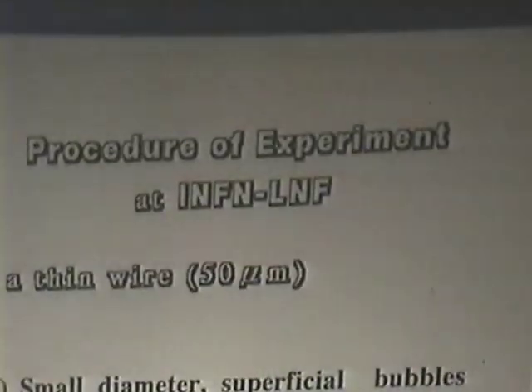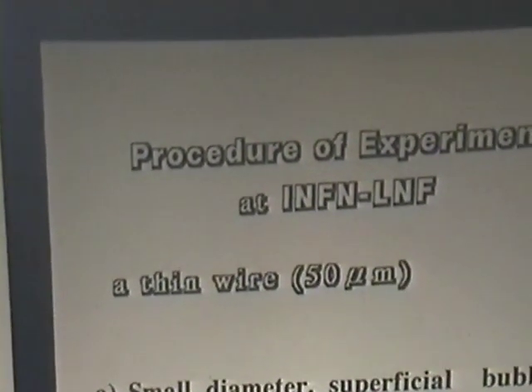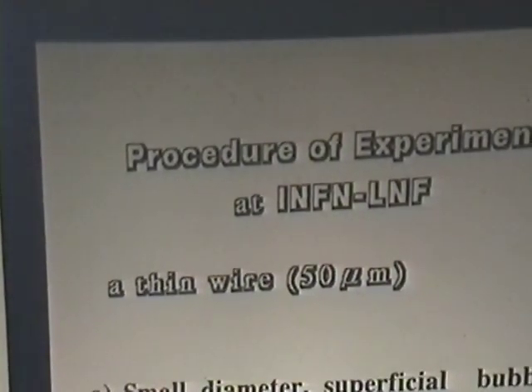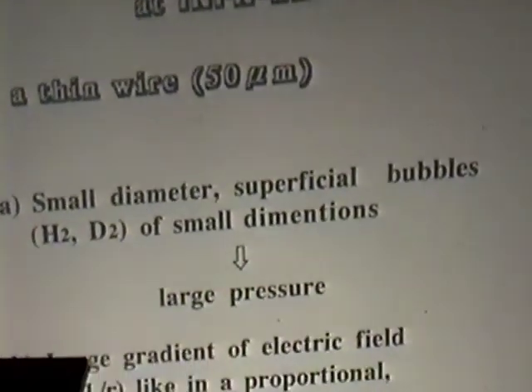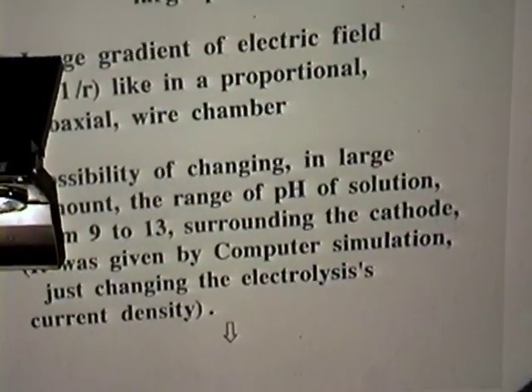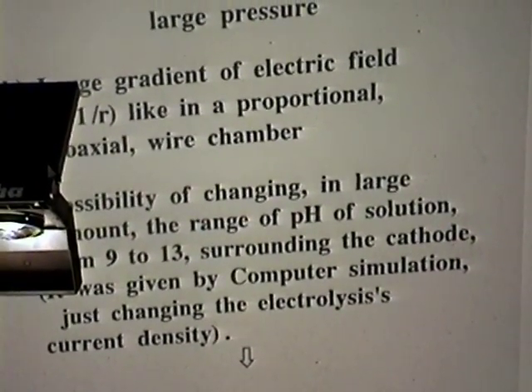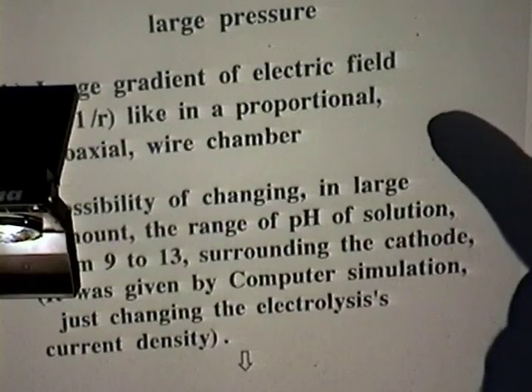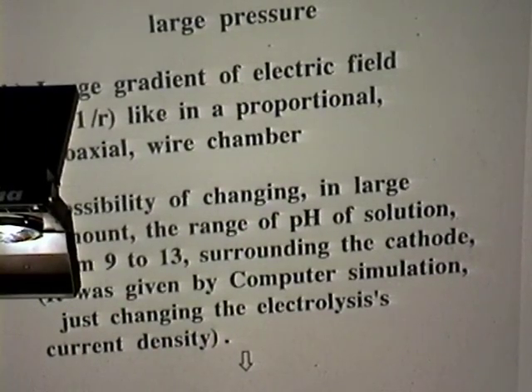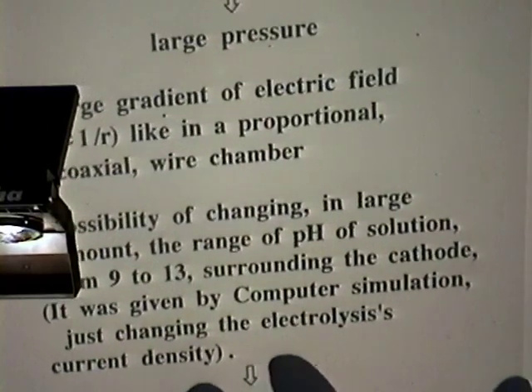The procedure uses thin wire. Thin wire means small bubble diameter, which means large local pressure that can help against the gas. Moreover, there is one more point: a large gradient of electric field inside the thin wire. This is one of the key points of the experiment. A large gradient of electric field, like in a proportional chamber for nuclear detection. Moreover, we can change locally the pH of the solution between 9 and 13, just by changing the current density of the cell. And we made a computer simulation about this aspect.